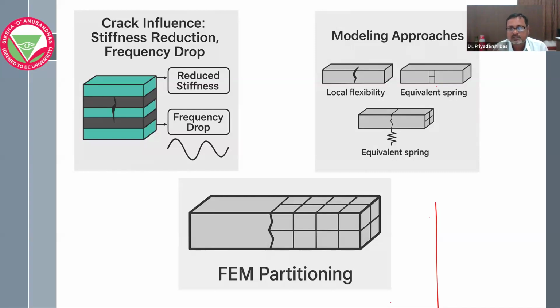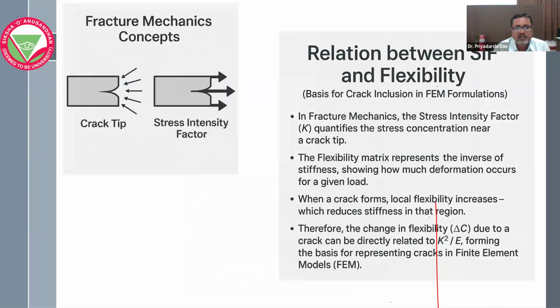So this can be drawn from the local modeling approaches, that is the local flexibility approach or FEM partitioning. FEM partitioning is quite effective compared to the local flexibility. And here the fracture mechanics concept is that at the crack tip, the stress intensity factor is higher. In fracture mechanics, the stress intensity factor quantifies the stress concentration at a crack tip. So how much stress is concentrated at that point? If the stress concentration is more, then the failure of the structure is imminent. That means the flexibility matrix will increase. If the flexibility matrix, or the local compliance, increases, that will reduce the stiffness of the structure. If the stiffness of the structure at that region is reduced, it will directly affect the structure and lead to the failure of the structure.